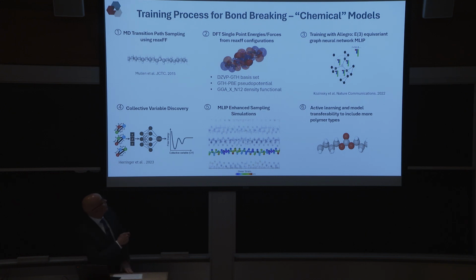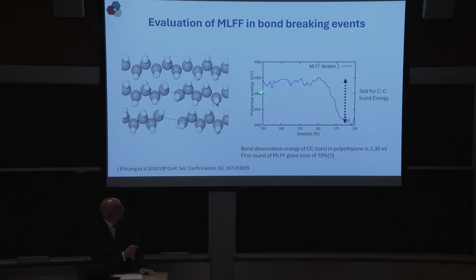So that's what we've been doing for all of these chemistries that I've shown you before. We start training the models using approximate force fields. We do the quantum mechanics. We train a network. We do a bias simulation. We do the DFT once again. We train the force field. We get it better, better, better. You do many iterations. And at the end, you have something that you hope works. So I'll just show you a little result for polyethylene, where we show that we can capture the energies at which these bonds break when you stretch it.